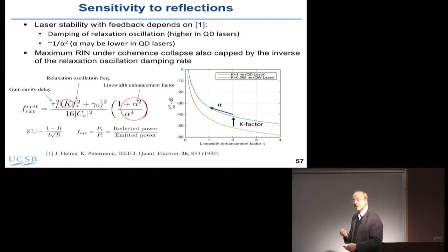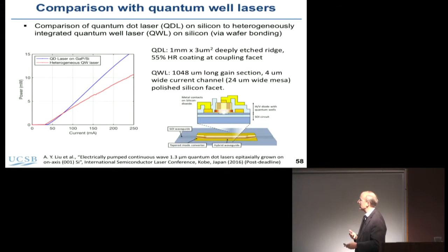And it turns out people have been predicting that quantum dots should be better than quantum wells in terms of being insensitive to reflections. And so the critical power written here depends upon the K factor, this dynamic relaxation factor, damping factor, and it depends upon the line width enhancement factor. And so both of those should be better for quantum dots than for quantum wells. So if you compare, the blue curve here is for a quantum dot laser, the red curve here is for quantum well, you should gain from the K factor improvement, and you should also gain from the lower line width enhancement factor. So this would show an improvement of, say, 15 dB, if that were the value changes.